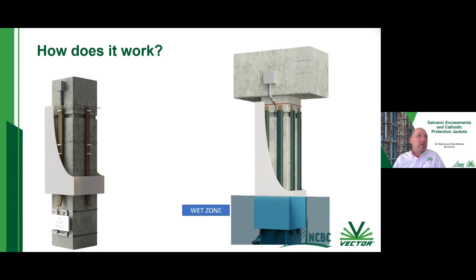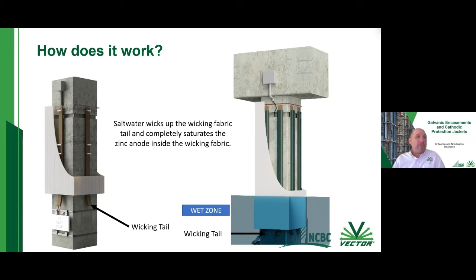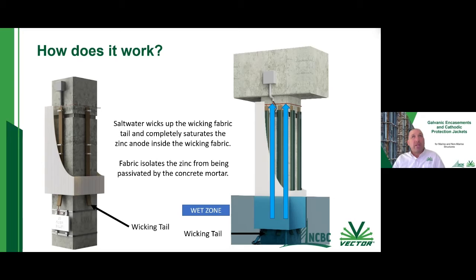You know, what are the differences here between the Tidal jacket. So for the Tidal Plus jacket here, we have our wet zone that's down below, same thing. And what ends up happening is we have our wicking tail. So these tails are basically sticking out the underside, or in the wet zone, of the pile. And what's going to happen is these wicking tails are going to actually allow the salt water to wick up and go farther and higher up on these zinc bars, and basically completely saturate these zinc bars and keep the zinc in an active state. So the fabric is also going to help isolate it, stop the zinc from actually contacting our concrete mortar and passivating that way. So what we've been able to do is basically bring the salt water higher up in the environment or within our jacket system. And so now we can actually activate the zinc higher up on this jacket system as well.